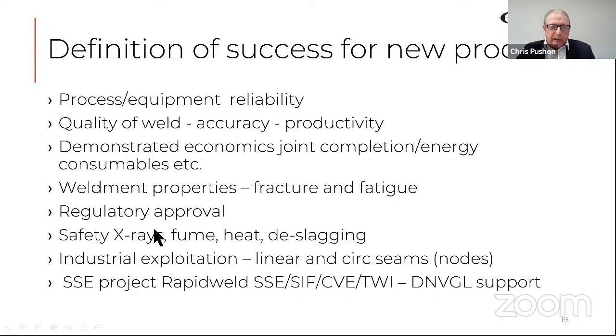One of the things that happens with the electron beams when they hit metal targets, they generate X-rays. So the only real concern for the adoption of the process in industry was showing that the X-ray enclosures were safe. And the process doesn't produce any weld fumes. It doesn't produce much heat. You can put your hand on the weld after you've finished welding, and you don't have to de-slag. You don't have to chip slag off, which is a risk in a factory.